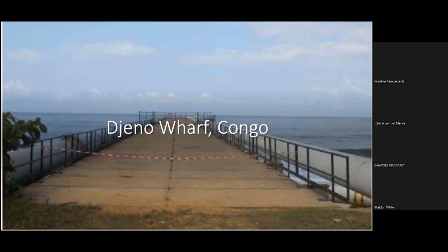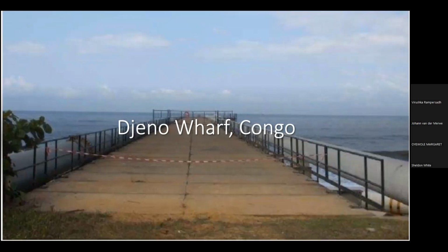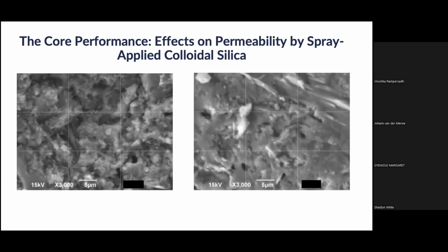So after it was in the water a year, we treated most of the wharf and left some of it untreated. A year later, so 2 years total time in the water, we came back and took some cores. The untreated concrete at a 10 millimeter depth is seen on the left here. This is a very small scale, a 5 micron scale here. You're looking at a total width of the specimen of about a third of a human hair or so. And you can see that the treated area on the right is much more dense looking.